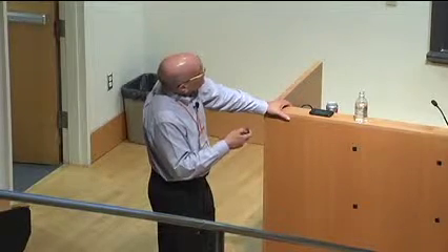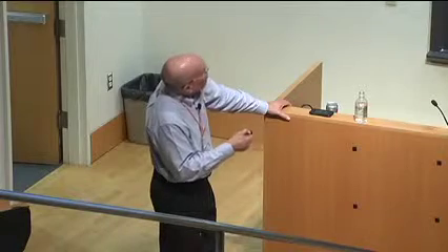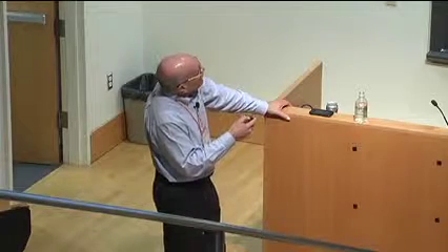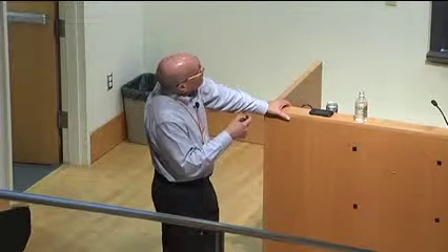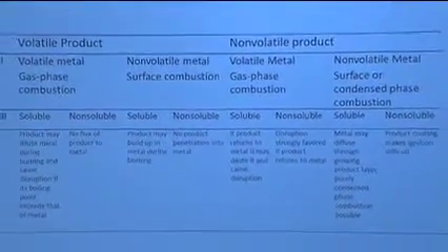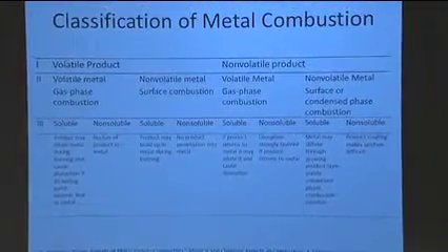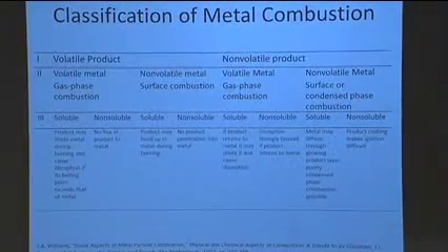Okay, and so to illustrate this a little bit further and to define this, this is really a classification of this process, and I again pulled this out of some of Forman Williams' work, which really follows Irvin Glassman's work. But really, the first discrimination that I just showed you was first looking at the energetics, whether or not the product would be in a volatile form or a non-volatile form. The second discrimination then would be to see whether or not there's enough energetics available to actually vaporize the metal itself, or does the metal remain as a non-volatile? And I can break this up for both sides. And then there's a third discrimination on asking whether or not the products that are being formed are soluble or insoluble in the original fuel.